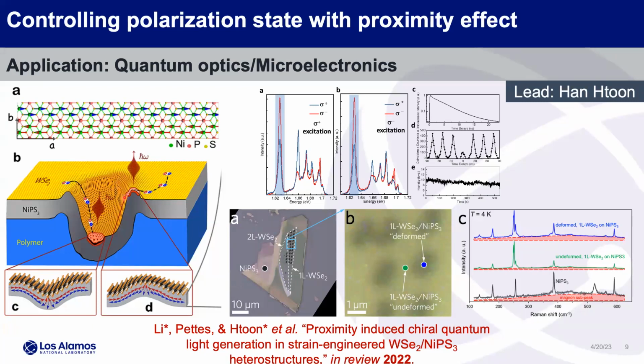Now, where that defect lies, we don't know. The postdoc, we spent a lot of time with him on this, and he came up with a nice cartoon showing it could be from here, it could be from the edge, it could be from somewhere else. We don't really know, but we usually get 1 or 2 defect lines that come out of this. The best circular polarization sample we had had 4 defect lines coming out of it. So there can be multiple, but the process by which we did this and the conclusion that we take out of it is still along the lines that strain is important.